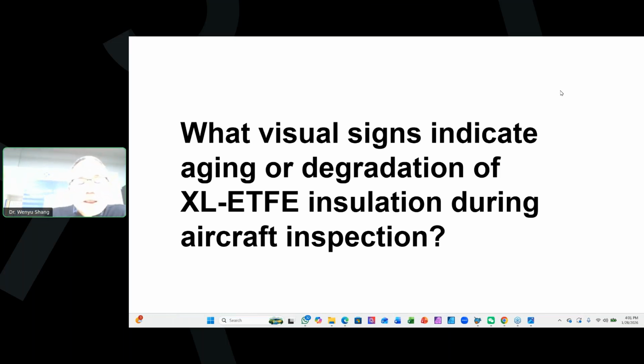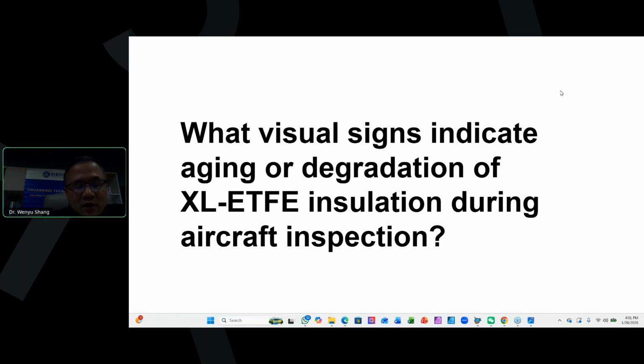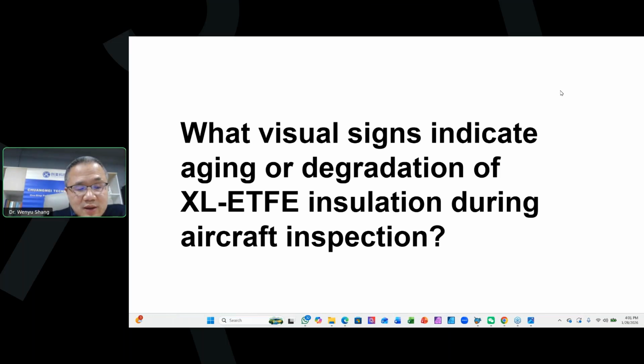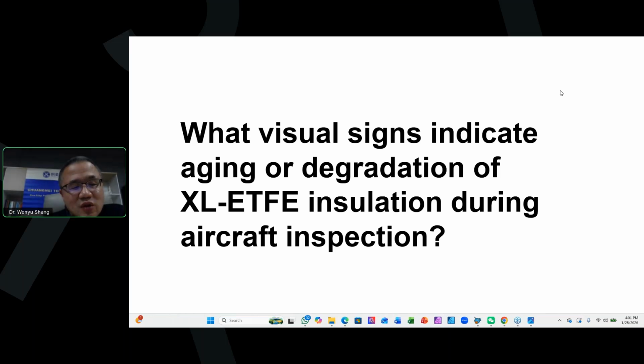So this is usually where the cable sustains the highest stress level, and over a long working time, these are the reasons causing micro cracks in the insulation material, and subsequently causing the working failure of the communication cable. So when you inspect a long-working-time cable, micro cracks or even some large cracks are one of the first aging signs you want to inspect on the cables.